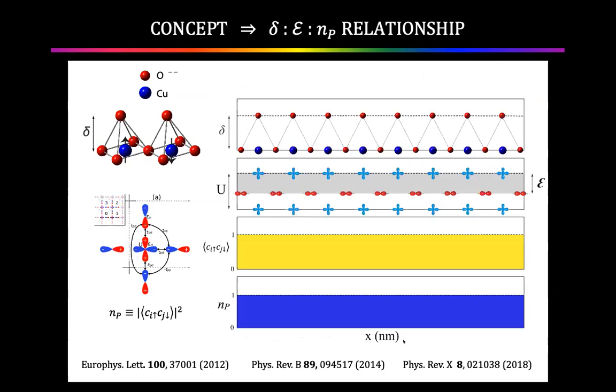All right. So now let's take the experimentalist view of this situation. The distance from the copper to the apical, let's call that delta. So here's a schematic of the plane. Oxygen, copper, oxygen, copper, oxygen, copper. Here's a schematic of the apical oxygen, here's delta. So here's a schematic of the energy structure of the plane in the presence of the apical. Then from the three-band DMFT model, one could predict what should be the amplitude of the pair field. We can't measure that, but we can measure the number density of pairs.